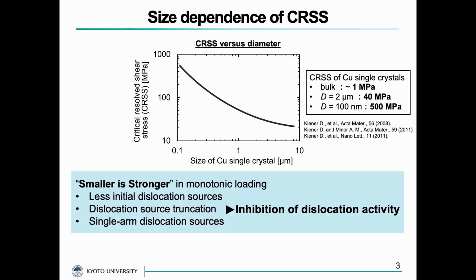Critical resolved shear stress is the yield stress resolved into the primary slip system of a single crystal, and shear stress is constant at the bulk scale. However, it is widely known that as the diameter of a single crystal decreases to less than tens of micrometers, it becomes larger. As for copper single crystal, CRSS of the bulk is less than 1 megapascal. However, as the diameter decreases to 2 micrometers, it becomes 40 megapascal, and it ultimately becomes 500 megapascal as the diameter decreases to 100 nanometers.